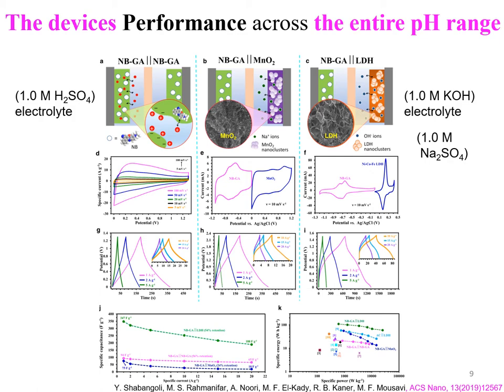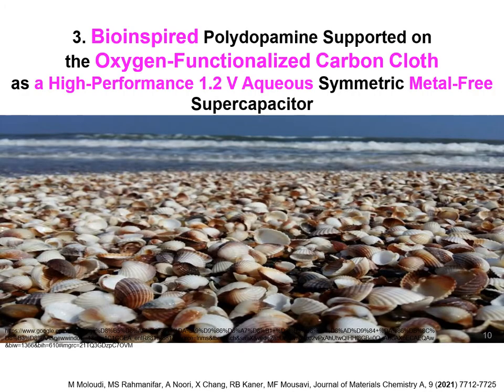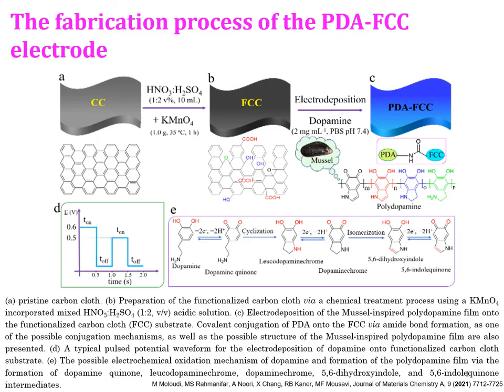This slide shows the fabricated three devices' performance across the entire pH range. In all these devices, the prepared composite serves as a negative electrode. In another approach, we were inspired by the strong adhesion properties of mussels, in which the amine and catechol moieties are responsible for their adhesion properties. We selected dopamine, which contains both the amine and catechol moieties. This slide shows how we prepared the polydopamine-functionalized carbon cloth electrodes along with the applied pulse potential pattern and the redox reaction that likely occurs during PDA film formation.